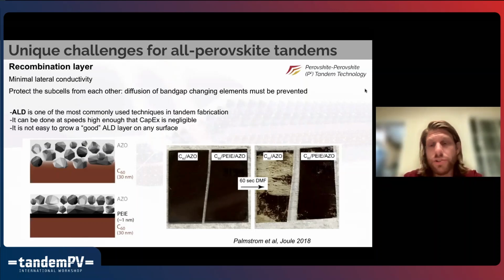It's also very difficult to grow a good ALD layer on any surface, and so we found it's important to modify, for example, a fullerene surface, because of course, how can you nucleate and grow a polar substance on a completely non-polar hydrophobic material like fullerene? So you can modify that surface to improve the density of your final layer.